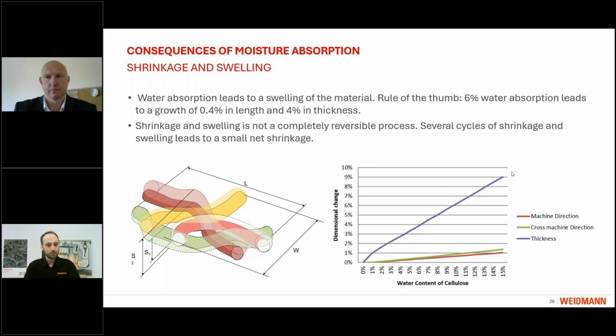What is also crucial is that the last step is this hot pressing of our material, and there we really force it into this state. And so whenever we cycle several times through shrinkage and swelling, this leads to a small net shrinkage, because the original state can really only be generated by this hot pressing.